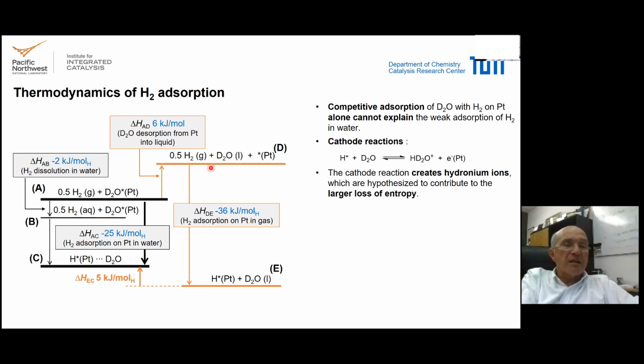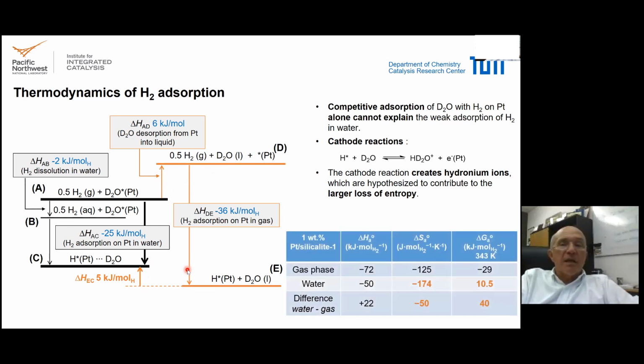So less stability. Now, this is related to the fact that when you are at the metal surface, you get an electrochemical reaction. That means that hydrogen, which is adsorbed, will partly be converted into hydronium ions and electrons on the particles, and it leads to a charge separation at that interface, the Helmholtz plane.